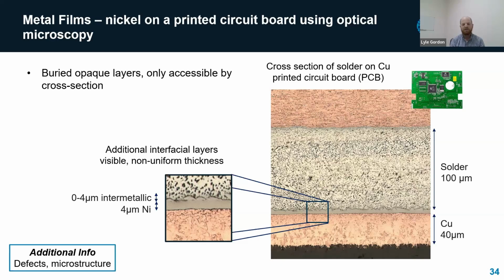So we can see a layer of solder, about 100 microns, on top of a layer of copper. And in between them, we have a thinner layer of nickel. But the beauty of the cross section is you can actually see these kind of islands of this intermetallic phase that have formed. And you can see that actually varies from some locations where there's almost zero thickness to about 4 microns. So if you were using any sort of broad beam approach, you might miss that kind of inhomogeneity of those buried layers. So the cross-section really gives you the visibility.